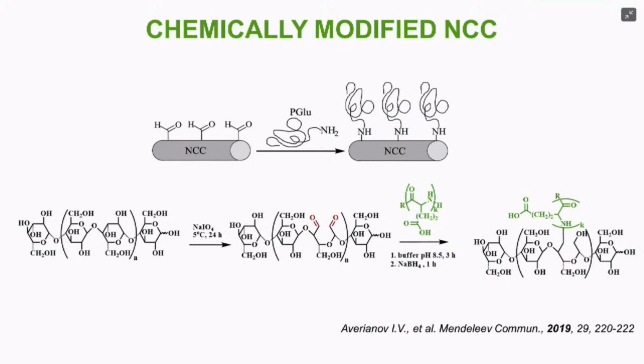So what we did, we oxidized nanocrystalline cellulose with sodium periodate, and then used the newly formed aldehyde groups to attach low molecular weight, about 2,000 molecular weight, polyglutamic acid to these molecules. And so this molecule, we can say modified cellulose, was used for further experiments.